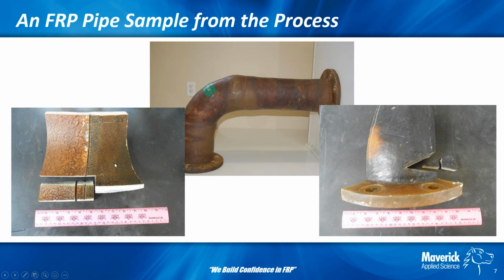So, the photos here that you see, on the left-hand side, this is the corrosion barrier. Somebody described this as a dried up riverbed. You can see some cracking of the corrosion barrier. I'll show you that this is going down into the veil layers, and on the other side you can see some of the darkness. This was one of the flanges where we cut out a piece as well. Generally, this system was, as I mentioned, a regenerative sulfuric acid service, and generally ran as weak acid between 10 to 15% concentration.